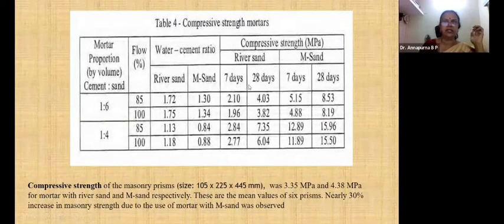The compressive strength, when we observe here, for river sand, for 28 days is showing 4.03, whereas for M sand it is 8.53. And even for 1:4, also 6.04 and 15.50 for 100% water flow, where the water cement ratio is more. For lesser water cement ratio, it is showing a higher strength of 15.96 and 8.53 compared to 4.03 and 7.35 of the river sand. So nearly a 30% increase in masonry strength due to the use of mortar with M sand was observed.